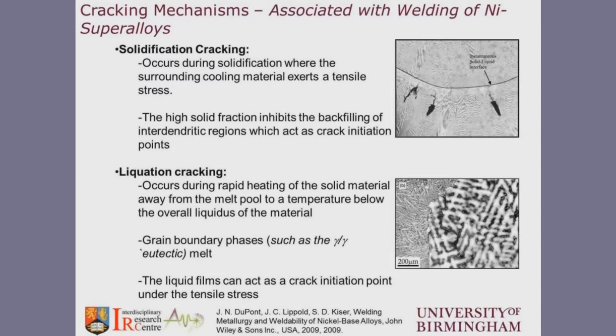So we're talking here about the material which is below the molten region, not just the molten region, but actually what's a little bit far away from, or a little bit close to the molten region, but not in the molten region itself. Some phases will end up actually forming a melt, or forming a liquid film, that then will form basically a crack that can act as a crack initiation point under the tensile stresses.